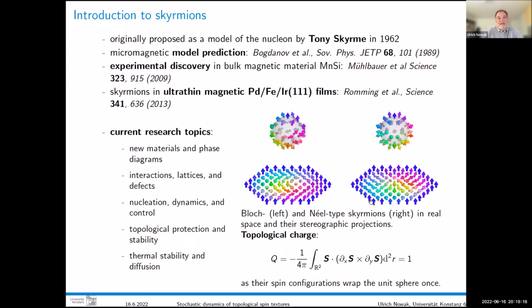And that can be understood a bit by a projection of this structure on a unit sphere. So if you see in this structure, all colors appear somewhere. So one could say that this structure could be mapped on all spin directions of a unit sphere. So every direction appears somewhere, the red one, the yellow one, and so on. And that is typical for a skyrmion, and that is what is quantified here with this so-called topological charge. So if it is 1, then in your spin structure, you can be wound around the unit sphere once.